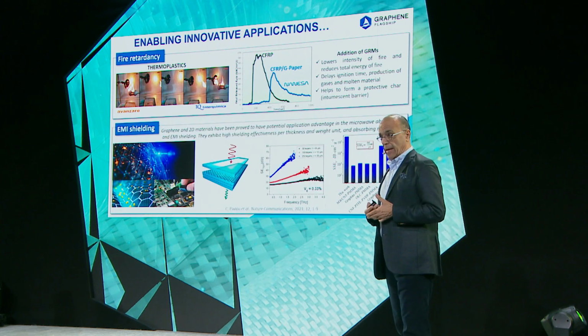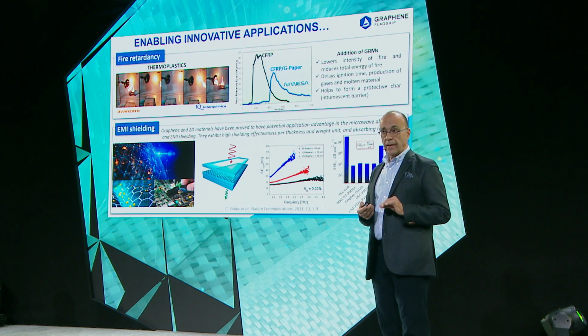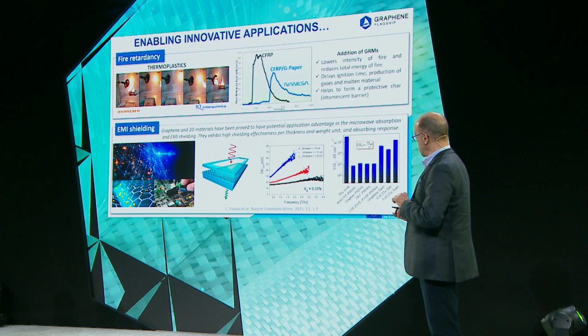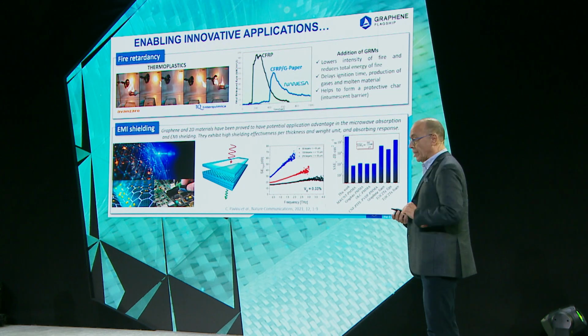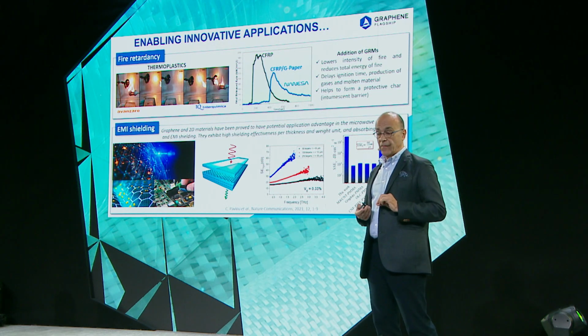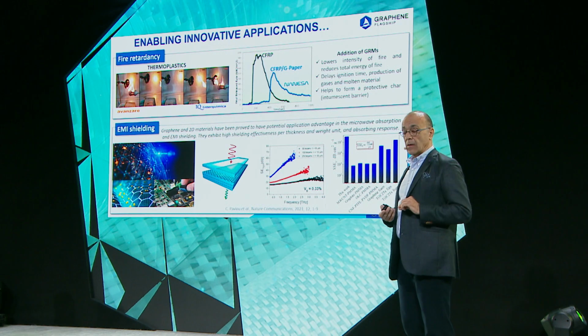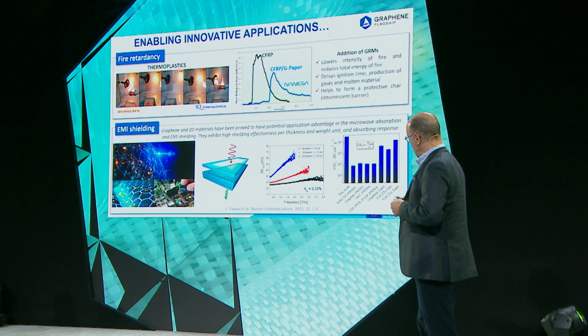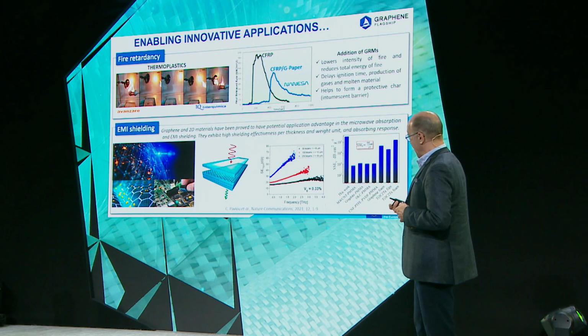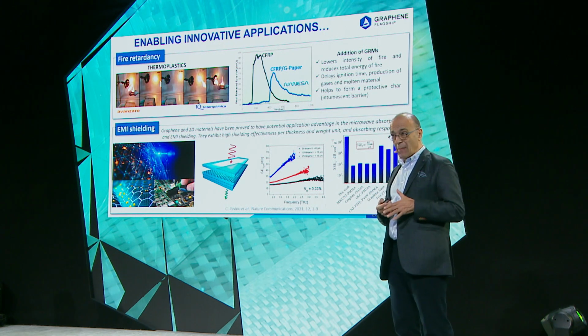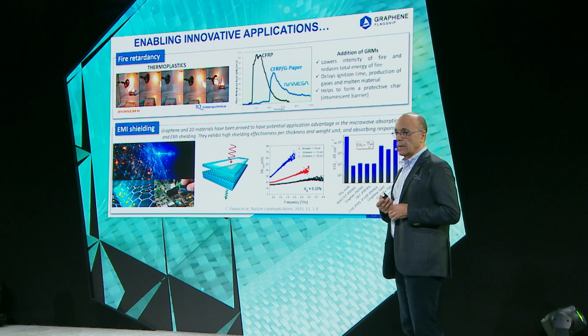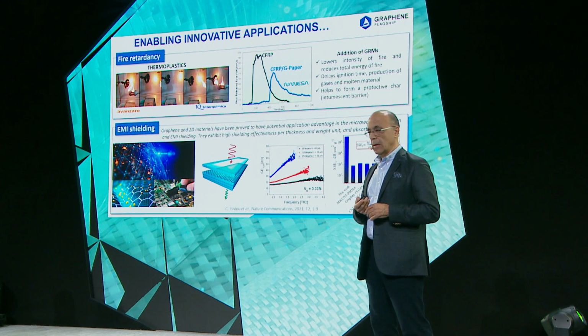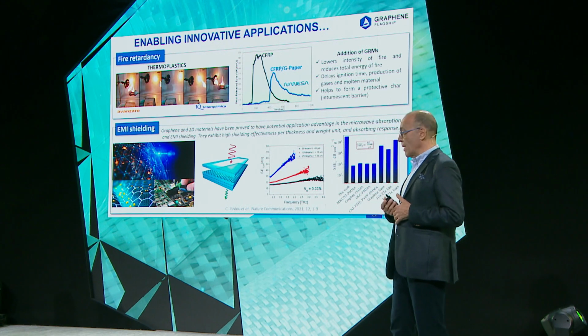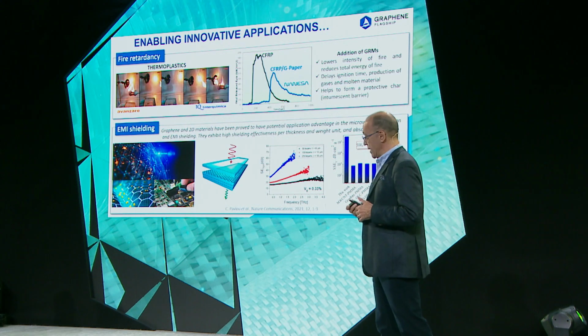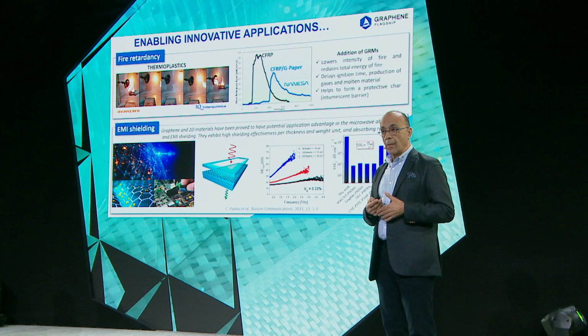EMI shielding is another area. It's very thin, absorbs radiation. So if you divide by the thickness, which is very important, and the size of the material, you will see on the right there that the effective EMI shielding is much better than any other competing structure, even MXenes or CNTs, etc. And this work has been done by us, from our own university, in collaboration with CNR in Italy.